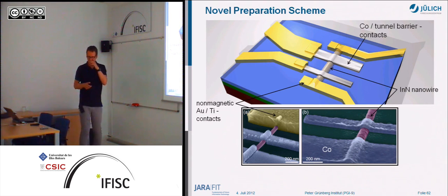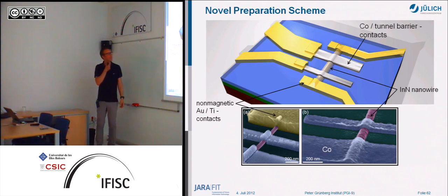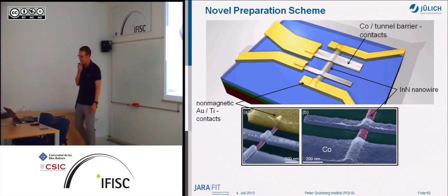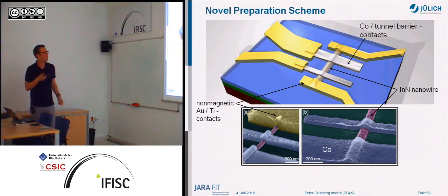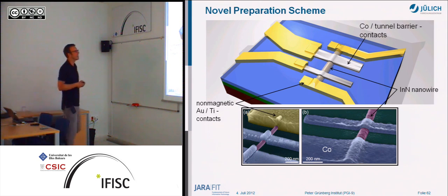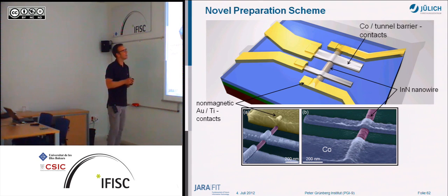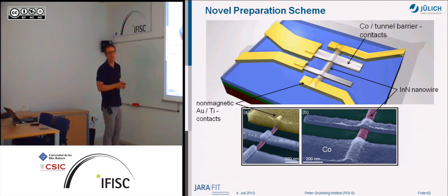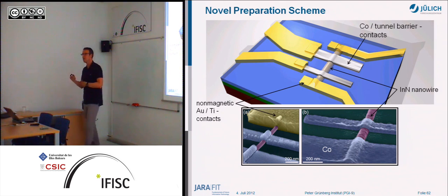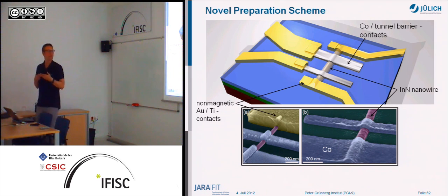What we're working on is that we try to inject electron spins into a nanowire, and for that we put ferromagnetic contacts on the nanowire. This is a semiconductor nanowire, and these are cobalt ferromagnetic contacts. The idea is to drive a current through this electrode, inject spins, which can be detected by the second electrode. That's the usual non-local method of detecting spin injection into the semiconductor nanowire.